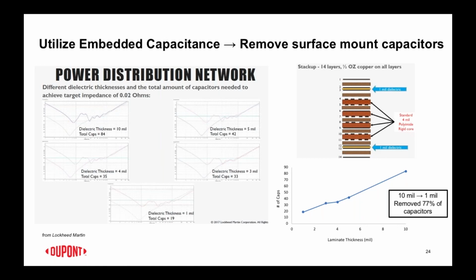Here's an example where we took a 14-layer board and used half-ounce copper in all the layers, and we started varying the thickness between the power and ground planes. I started out with a very typical thickness, 10 mils between, and they needed 84 total decoupling capacitors to kind of get the job done. If you lower that down to 5 mils, the caps that you need now is only 42. You go down to 4 mils, you get 35, 3 mils, you get 33, and then you get down to 1 mil, and it's 19.